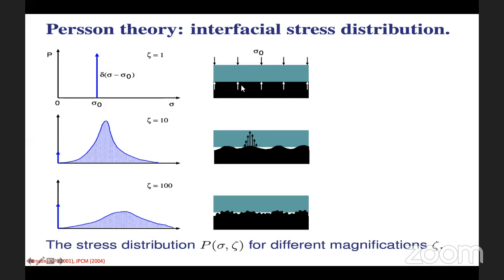But in Persson's approach, you start magnifying the interface, and you will see that there are areas where there is no contact, and areas where the asperities make contact, which are regions of high pressure, while the non-contact areas will have a region of low pressure. So the stress distribution at the interface now broadens, and the zero stress is also increasing, because you will have many different non-contacting areas. When you further increase the magnification, short wavelength surface roughness appears, and it will broaden the stress probability distribution, and at the same time increase the non-contact areas.